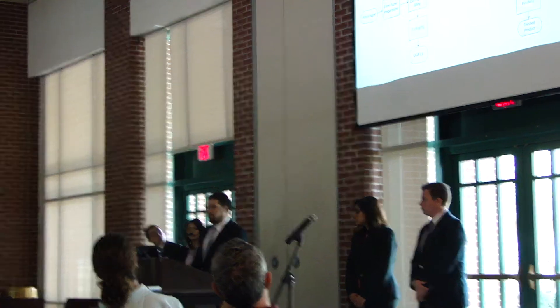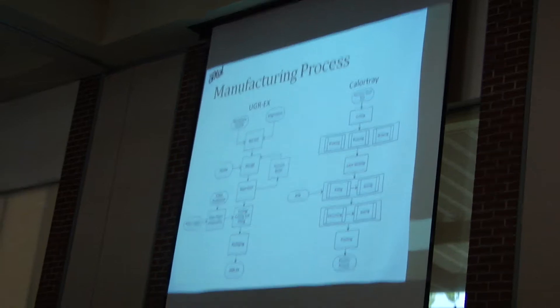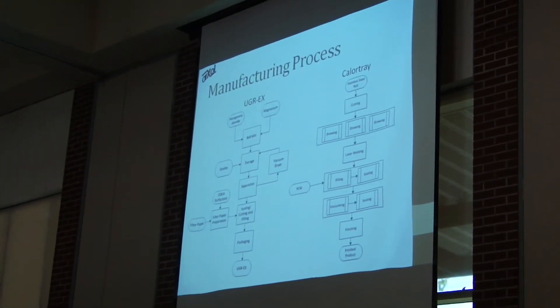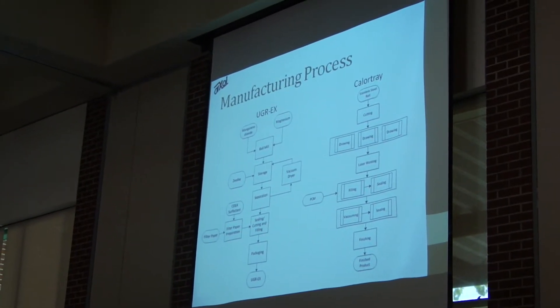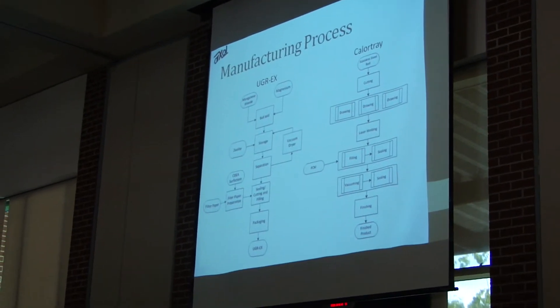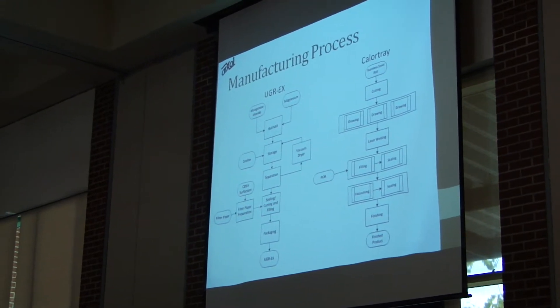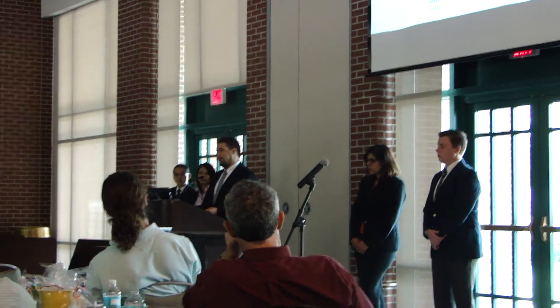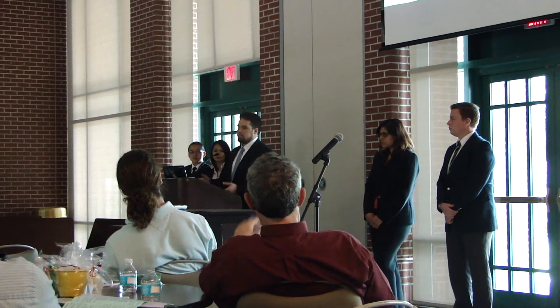For the manufacturing process of the UGREX, you start with magnesium and manganese dioxide. These are alloyed together in a ball mill and combined with a desiccant, then put into intermediate storage. Filtered paper is treated with surfactant and dried, set up into packets, filled with the reactive mixture, sealed, and then enclosed in a watertight bag so they don't get accidentally activated during storage or transportation.